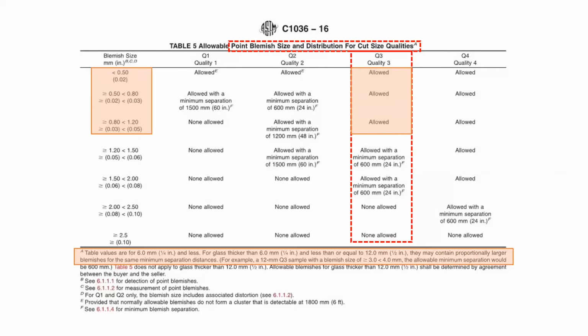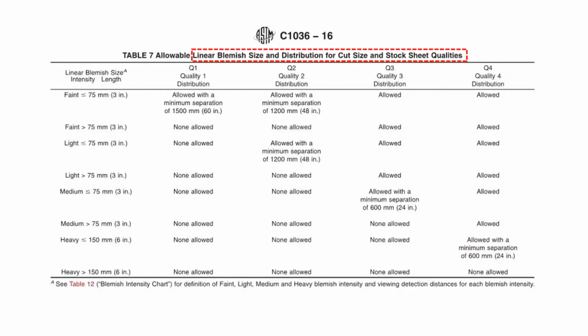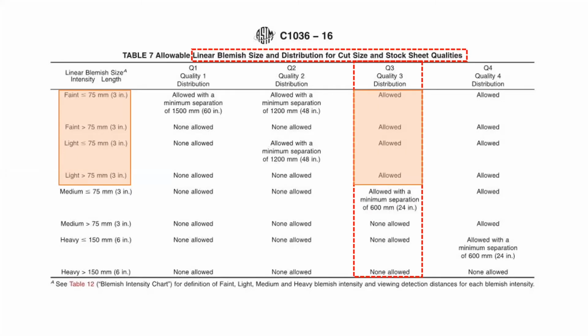Something to point out is this particular table was developed for 6 millimeter thick glass, nominally 1/4 inch thick glass. For any glass that's thicker, they're allowed to contain proportionally larger blemishes, and there's an example given in this footnote of the table. Then for linear blemishes or scratches, rubs, and the like, there's a similar table. And again, there's separate viewing distances for these types of blemishes, several different distances. If you can only see the blemish from a very close distance, they may be allowed in any quantity at all. But from further viewing distances, if you can only identify them at that location, they need to be separated by 24 inches. If they're identifiable from the furthest viewing distance, they're not allowed at all in some cases.